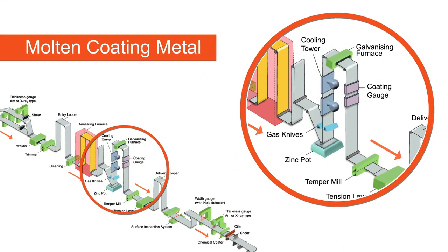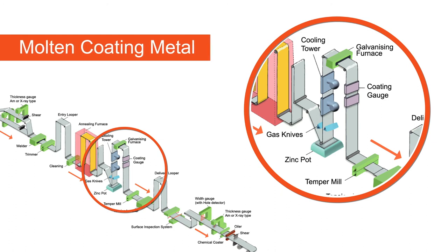A bath of molten coating metal being applied to the steel surface. Gas knives to wipe the excess coating metal and obtain the required coating weight.